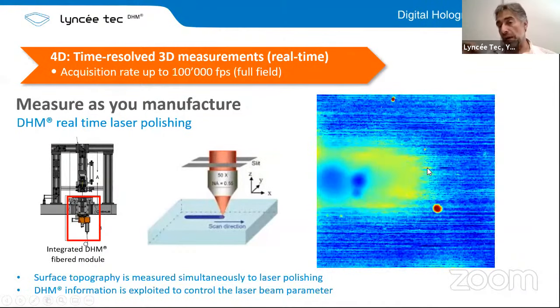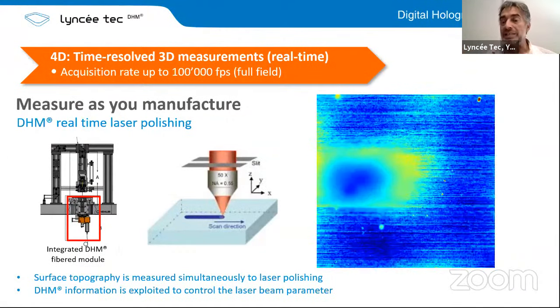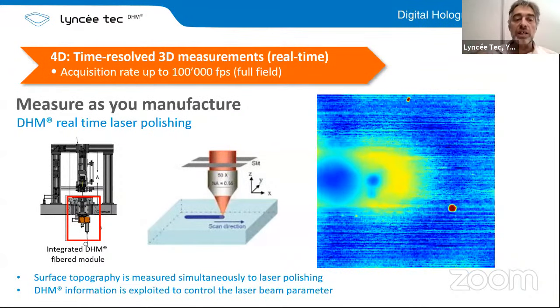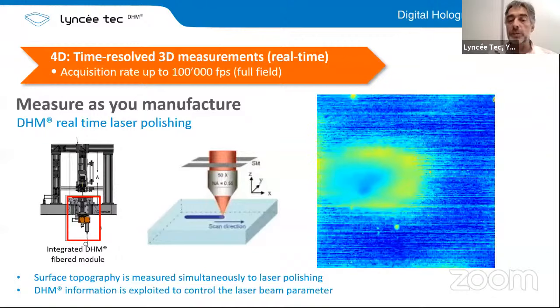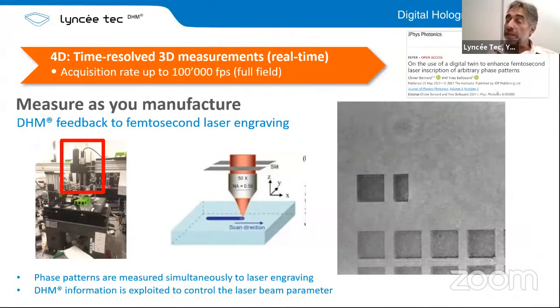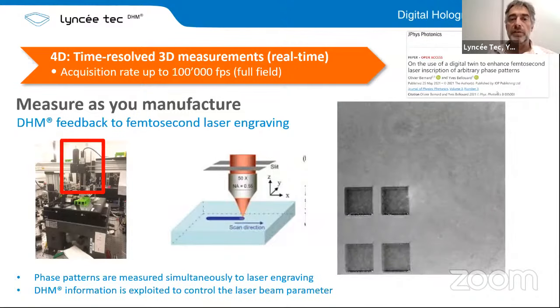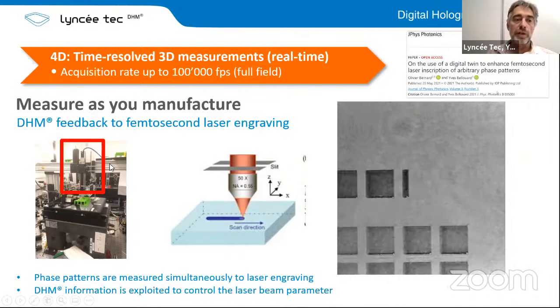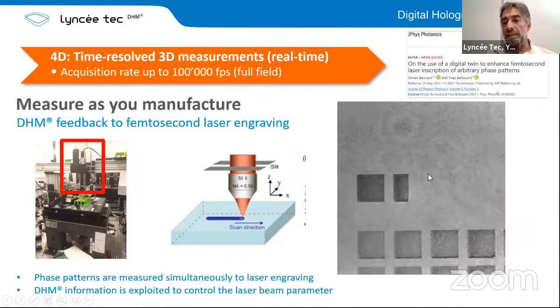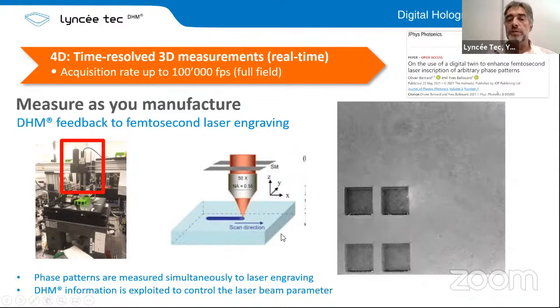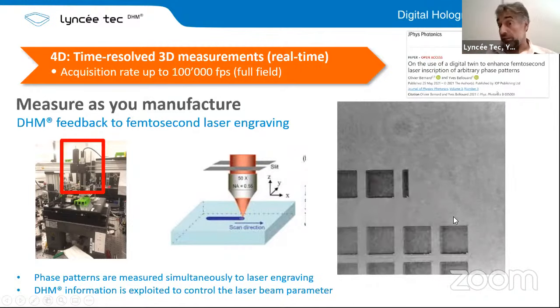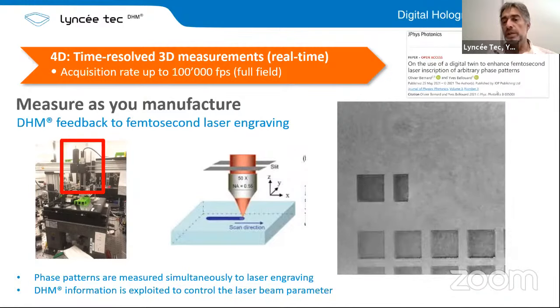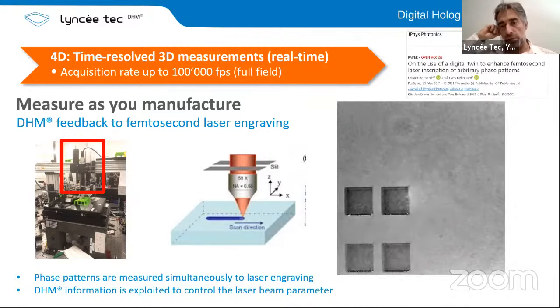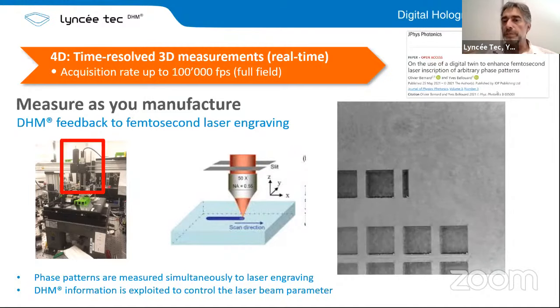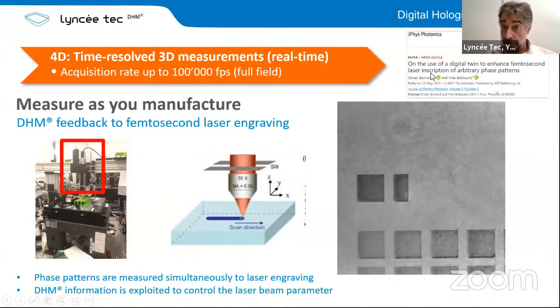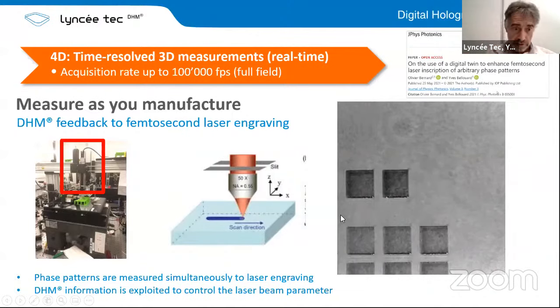So this map, actually it's a topography map, so color encodes height with nanometric vertical resolution. So the DHM information here is exploited to control the laser beam parameter in real time. That's a similar application here as well for femtosecond laser engraving. So we have also a small model which is integrated here, and we measure the change of the phase induced by the femtosecond laser engraving exactly when we measure. So depending on the material and the beam parameters, we can really control and give the feedback, and then it can enhance the quality of the laser inscription of arbitrary phase pattern. This has been well demonstrated.